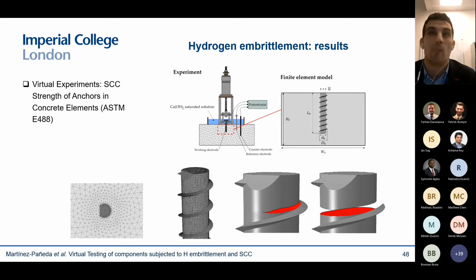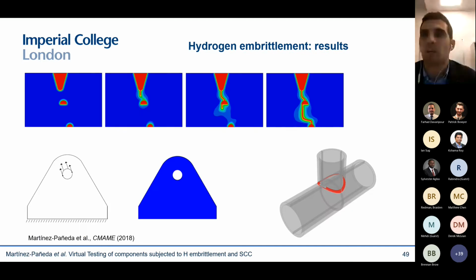This is an example of a rather complex test that involves a metallic screw inside of concrete. You know that hydrogen embrittlement is quite problematic for screws and bolts. So this is one classic example, where you expose the screw to a quite aggressive solution. With our numerical model, we can determine exactly what concentrations of hydrogen and what hardness of the material will trigger failure, and we can capture the entire failure of the screw. This sort of agreement with experiments gave us confidence to tackle more practical engineering problems, to enable the virtual testing vision that I mentioned before, and that is in the title of my talk.